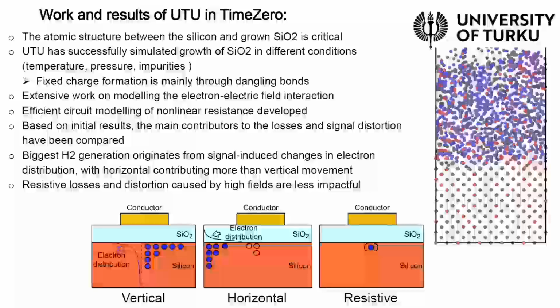And the initial results show that the biggest second harmonic signal generation comes from the signal-induced electron distribution on the wafer, and mainly so in the horizontal, the wafer plane direction. The resistive losses and the high fields have a smaller impact on the harmonic generation.